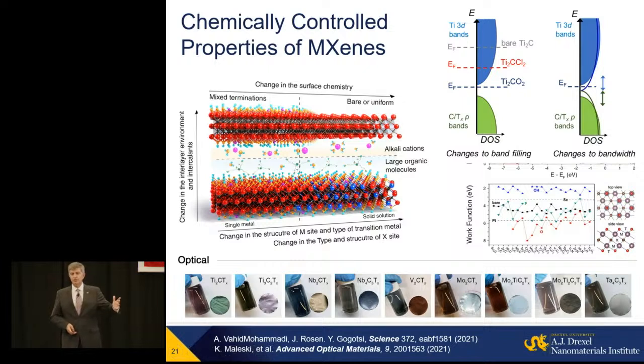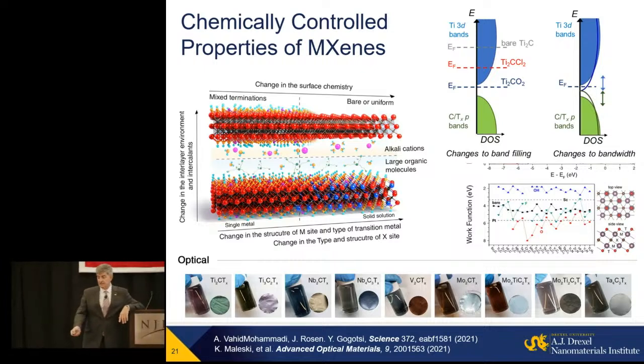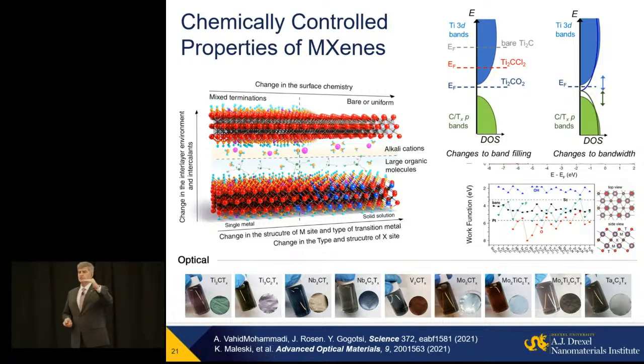You inject charges into gold or copper, and properties do not change by a dime. In MXene, for example, you replace oxygen with hydroxyl. Oxygen takes 2 electrons from the transition metal. Hydroxyl group takes 1 electron. And you can do it by applying about half a volt charge when you have protons between the layers. You protonate, deprotonate the surface. And the work function changes, for example, from 6 to 2 electron volts. So you have a metal, the properties of which you can tune like a semiconductor.